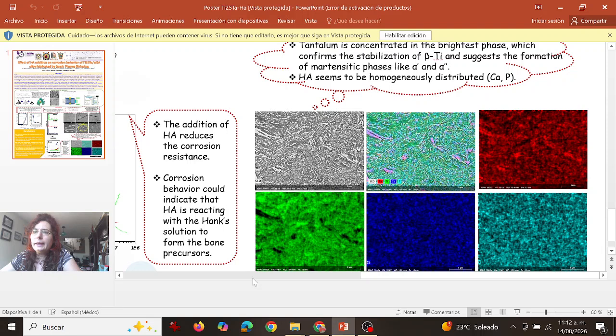All right, and in here, for example, for the hydroxyapatite, we have the components of the hydroxyapatite, so the calcium and the phosphorus. And what we can observe from these two microscopic images is that the hydroxyapatite seems to be homogeneously distributed. Same, yes. And the titanium is in green in here. All right.